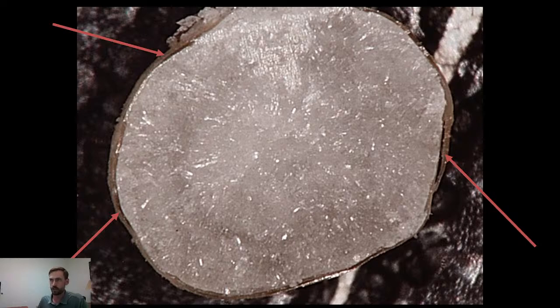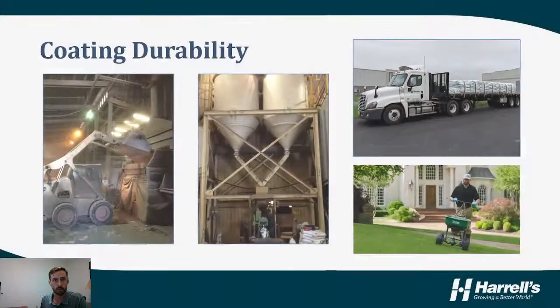So as a comparison, this is another material that's actually out in the market and has a different technology altogether, has a different chemical makeup altogether, but you have a urea substrate, you have a polymer coating, but what you don't have is the perfect adhesion around the nutrient substrate with the polymer coating, and in fact you have these small air gaps. And those small air gaps give you an opportunity for disruption to the polymer coating, which will lead to unpredictable release of the coating. And I'll show you a data example of that here in a couple of slides.